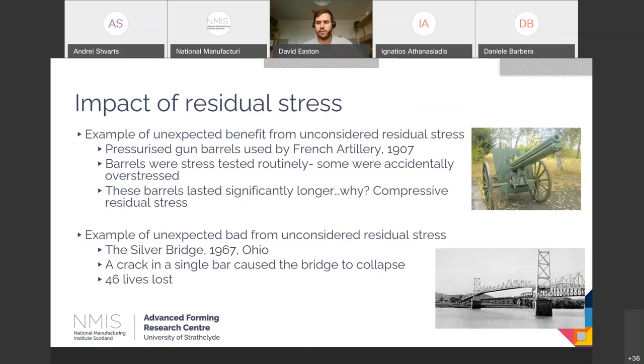And upon investigation, it was found that the reason for this failure was residual stress, which had caused a crack to propagate and then grow, and eventually for the beam to fail. So it's for reasons like this that when we're talking about situations where people's lives could be at risk, we need to consider residual stress.